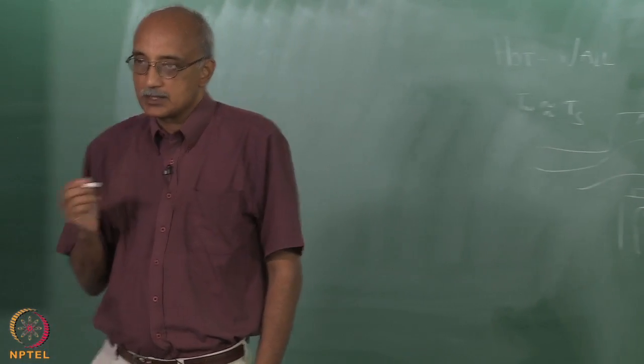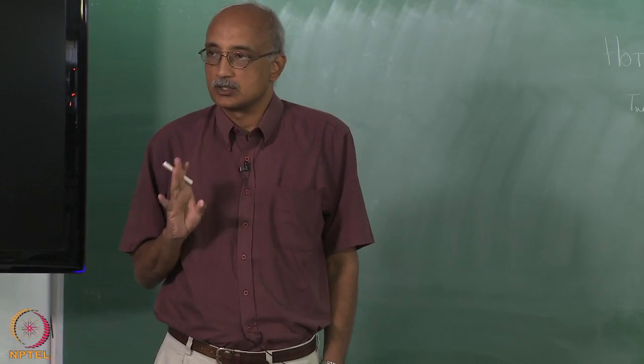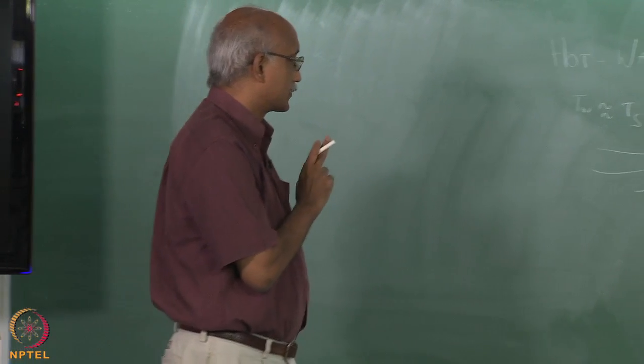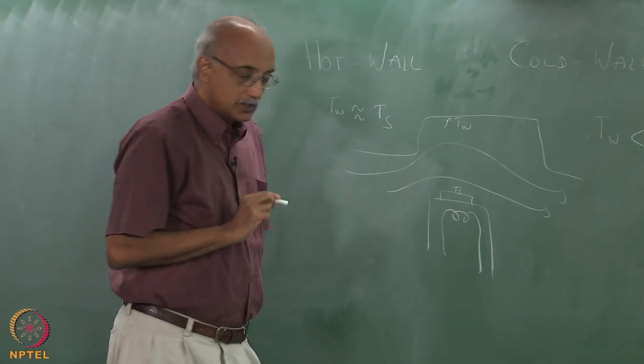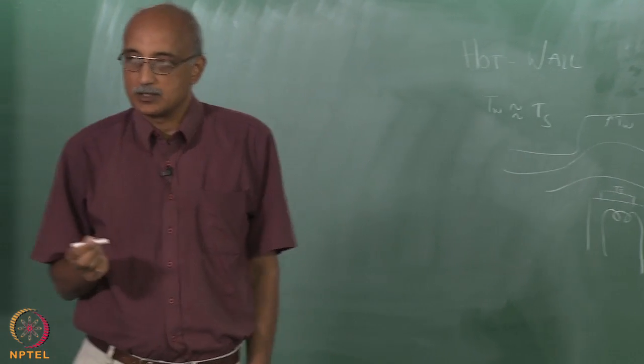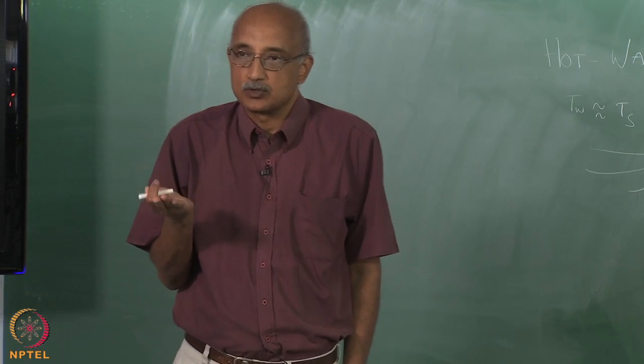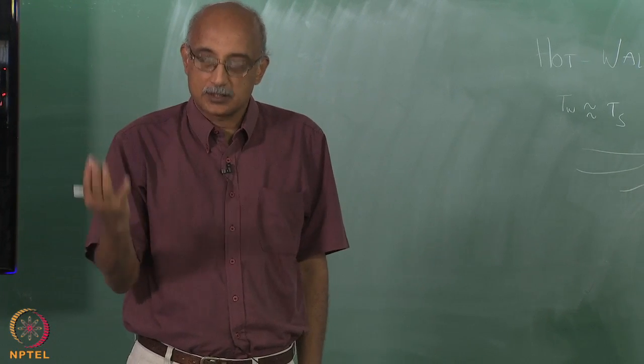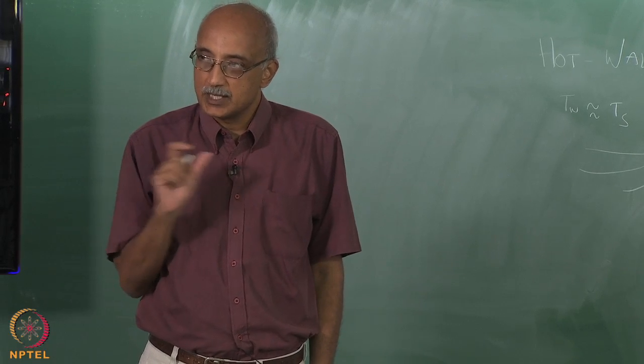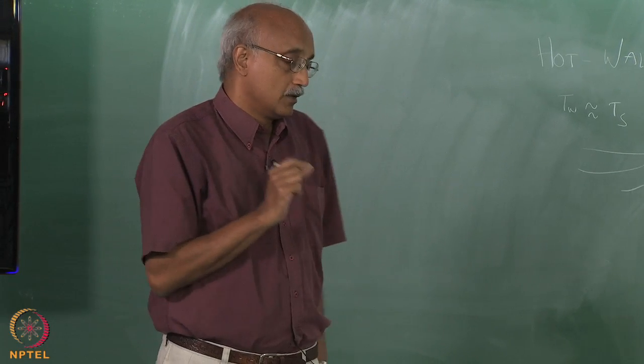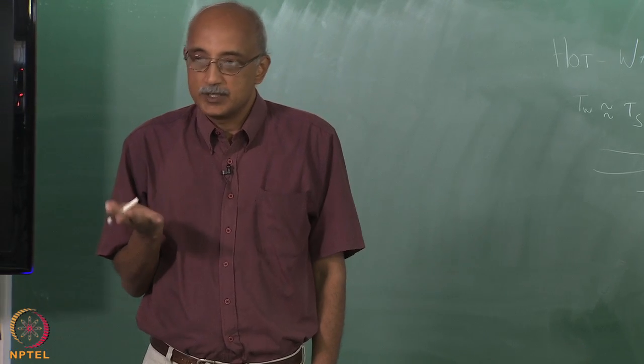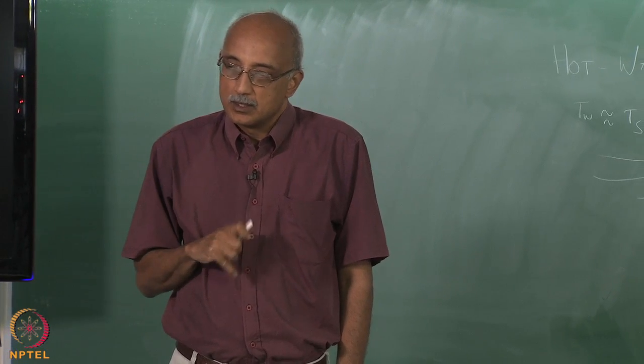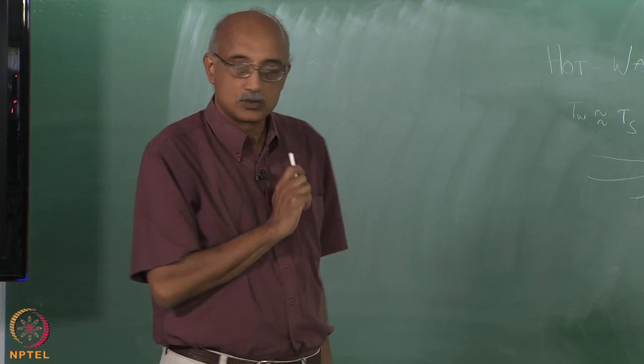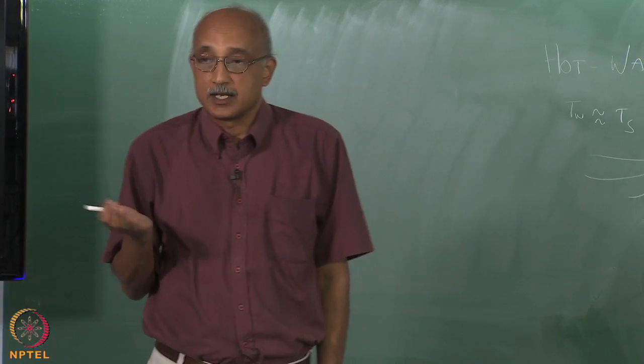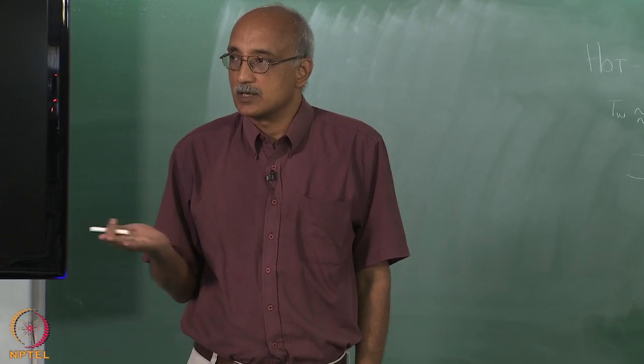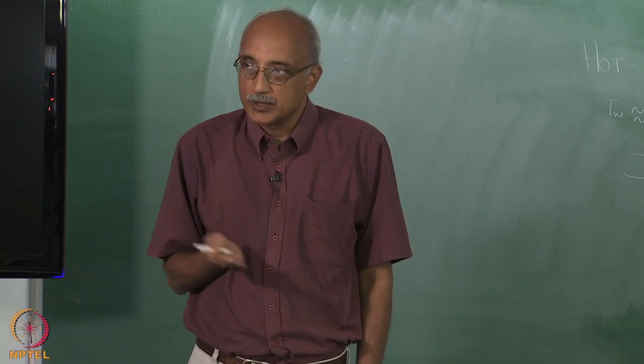Now, when you look at these two cases, what are the advantages and disadvantages that you can think of? When the wall temperature is approximately equal to the substrate temperature, essentially what that means is you are not heating the substrate too much, because you expect that the reactor itself will be kept fairly close to room temperature. So, when we say that the difference in temperatures is small, what we are talking about is that the substrate is not being heated to a very high temperature. Now, what is the biggest benefit to doing it this way? Well, first thing, there is an energy conservation, right? The hotter you have to heat, the more energy you have to supply. So, if you can make a process run at a lower temperature, you should always be happy.